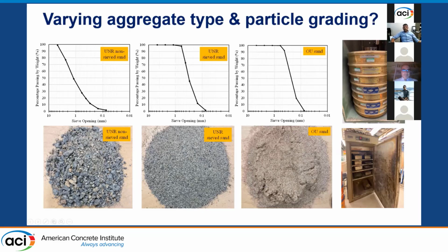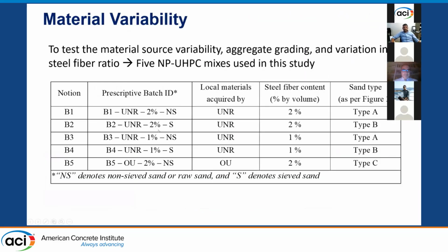So we did this as well, and putting all these things together, we had 5 batches that we tested: 2% and 1% steel fiber, using our non-sieved and sieved aggregate here from the Nevada region, and then the Oklahoma one, the materials that we got from them for reference purposes.